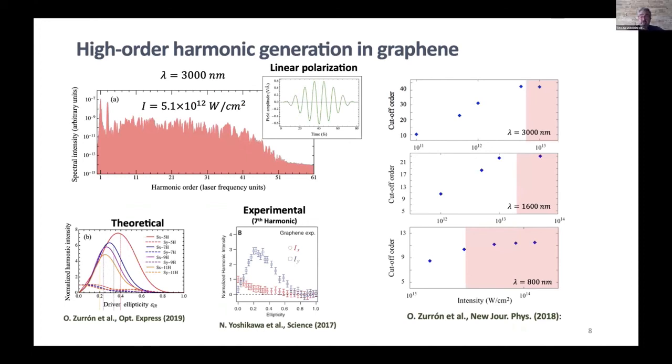The limitation will depend on the wavelength, of course. So depending on the wavelength, you can scale and obtain results at lower or larger intensities. What we can see for that is that the high harmonic emission is optimized in the mid-infrared regime, as you can see here. Because if you are in the near infrared, you can reach the damage threshold without reaching the maximum cutoff.